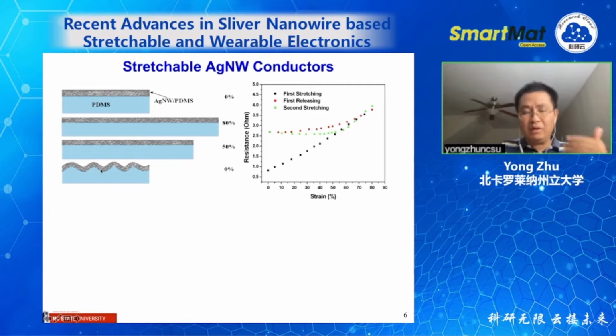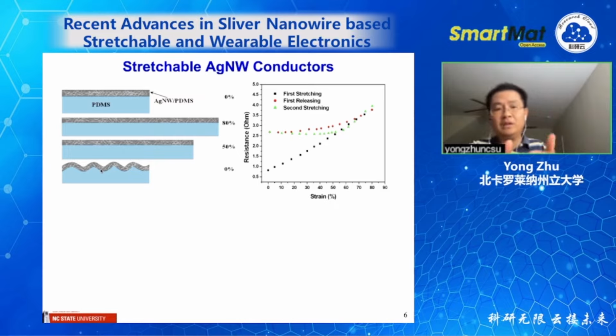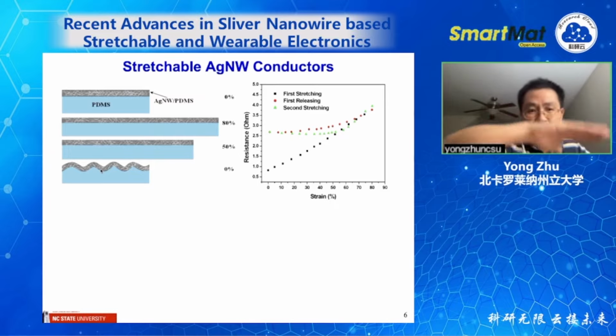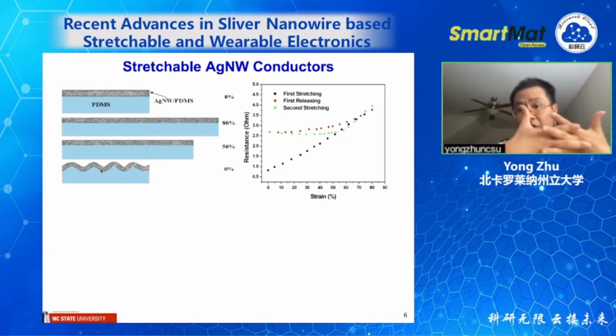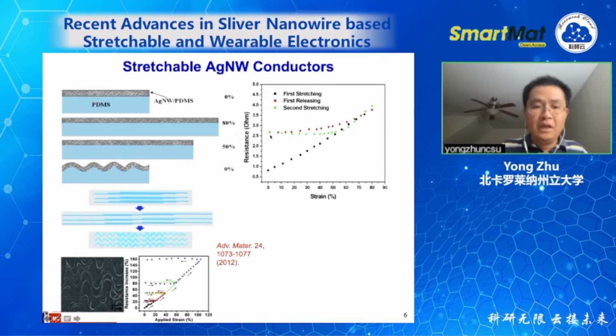And that's what we want. This is very important, very similar to the accordion bellows structure we talked about. So when you stretch, let's say in the second stretch, you essentially flatten this wavy structure without further sliding between the wires or between the wires and the matrix. That's why there's no resistance change.